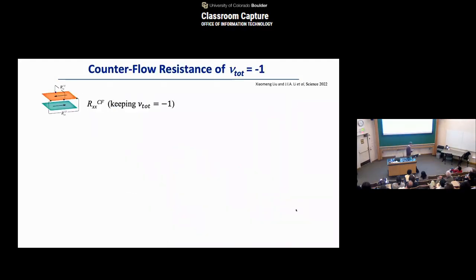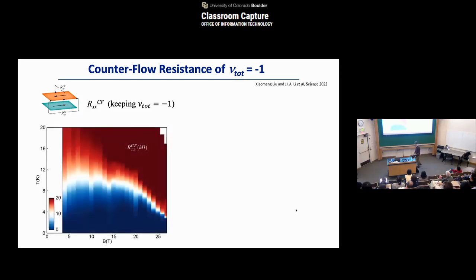So in this experiment, we have this graphene double layer. I just put this at total filling equal to 1, which means each of the layers is partially filled, about half filled, right? And then keeping that condition, I'm going to change my magnetic field and the temperature, and show how the counterflow resistance changes. And this is the phase diagram. I told you that when exciton condensation is happening, counterflow resistance goes to 0. Indeed, at low enough temperature or magnetic field, within this range the counterflow resistance is very close to 0, right? And as you go to higher temperature, the counterflow resistance becomes finite.